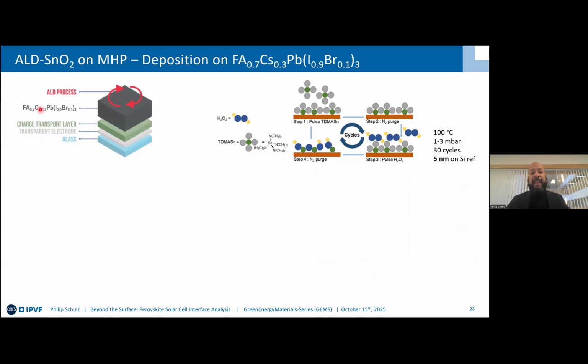So we start off with this double cation multi-halide perovskite and run the ALD process on top. This means you pulse first your metal organic precursor, which in that case here is TDMASn, so tetrakis-dimethylamino tin. You then purge with nitrogen. You then use your H2O2 for oxidizing the film, purge, and then rinse and repeat. You do this in order to get to a nominal thickness, in that case of 5 nanometers on silicon reference. So given the fact that you would need to have the material also stick to the perovskite in the same fashion and manner. Something that is not necessarily given, but that we can calculate from our experiments.